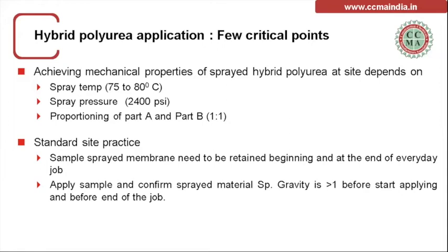When we see the spray equipment of fast cure polyurea, it's a reactor which will be spraying the material at 75 to 80 degree temperature. Not only in the machine, before spraying, the entire heat insulated hose length, the material travels through the hose at 75 to 80 degree temperature. And when it comes out of the gun, the ISO and amine mix has to be maintained at 1 to 1.